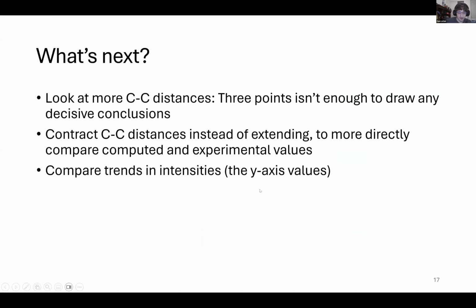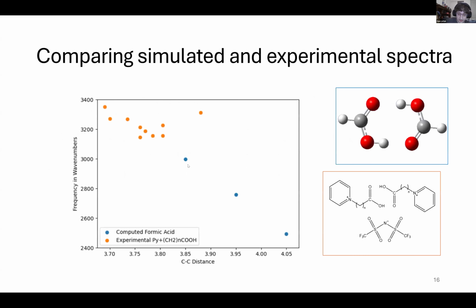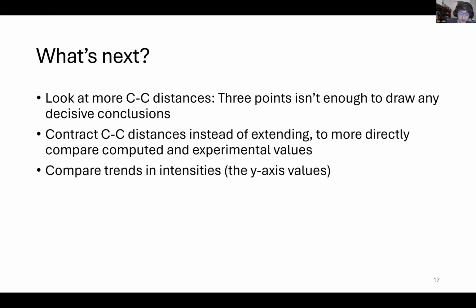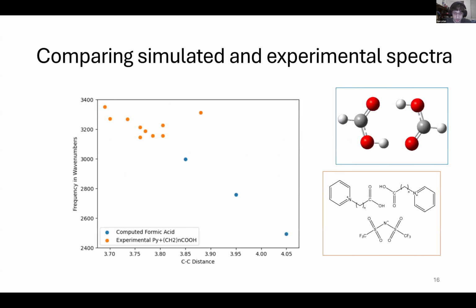So what needs to happen from here? Well, I've only used 3 points in my graph. I definitely would need to collect more data for that. 3 data points isn't enough to say decisively that this is what is happening. You might have noticed that I was using CC distances that are a lot bigger than the ones for the molecules that were actually measured, because the different molecules have different natural CC distances. So it would be nice to shrink that formic acid down instead of extending it, and make sure that it actually matches these orange points that were measured.